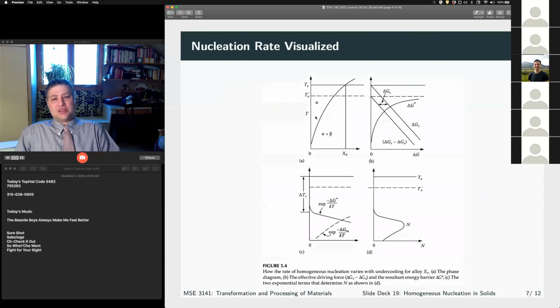So what do we get? Right? You can ignore this figure here, figure B. This is super confusing and it's not really talked about in your reading either. So just ignore that. But the key important idea is here, right? In figure C. Okay? As we go lower and lower in temperature, we know that our driving force for nucleation increases, right? Same as solidification. The greater our undercooling, the more likely we were to be able to overcome our energy barrier, right?